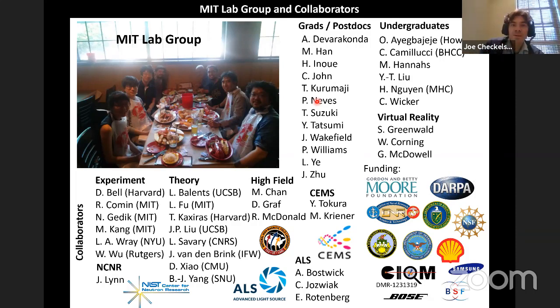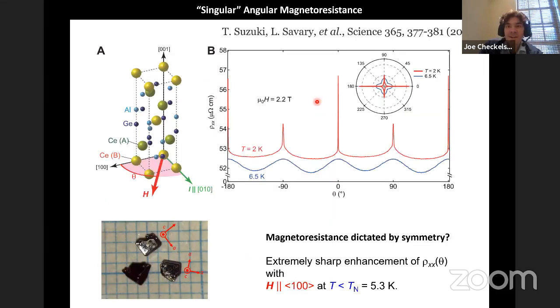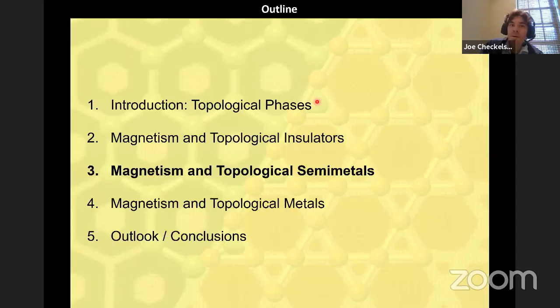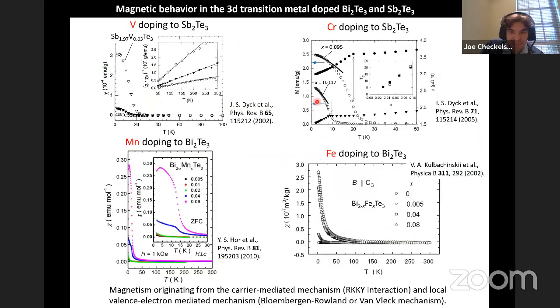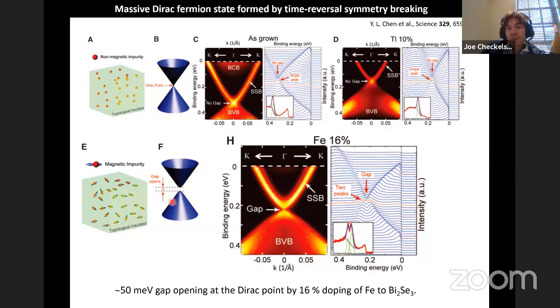Yeah. So there, what I will say, especially because I know this is recorded, is that there is some controversy, or anyways discussion, about the origin of magnetism in these systems. And I think somewhere I even tried to hedge my bets by mentioning that it's either this RKKY manner, or other people have talked about a valence electron mediated magnetism, a so-called Van Vleck magnetism. So I think there is evidence for both possibilities. I think one way of understanding how it could even arise in the context of RKKY-like interactions is if it was still driven by the surface electrons in these systems, right? So what you could imagine happening is that if you have this surface spectrum, if you even forget about bulk magnetism, you could have a magnetic instability on the surface by which, if the Fermi level is, for example, inside this gap, you could get ferromagnetism driven just by the electronic energy gain of the surface electrons by being able to open a gap.